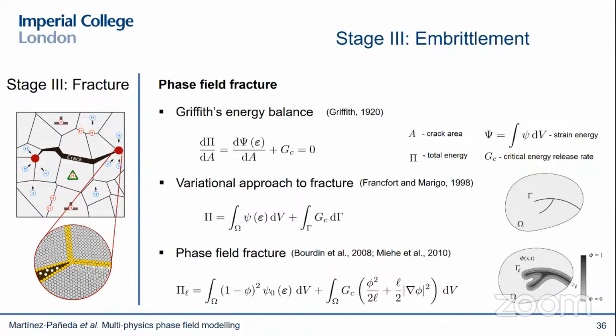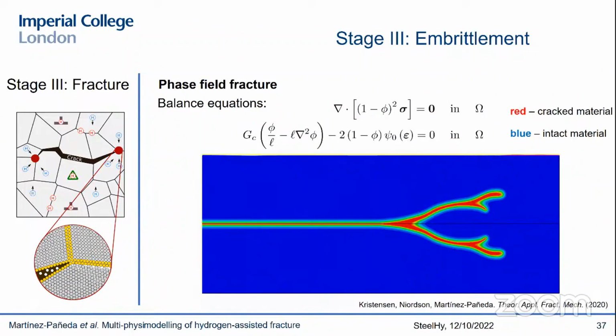So here is the balance of the strain energy density and the fracture energy, the material property that measures the resistance of the material to fracture. And just by solving this additional differential equation, you can capture very complicated cracking phenomena on the original finite element mesh and without any convergence problems. So all the results are based on Abaqus.